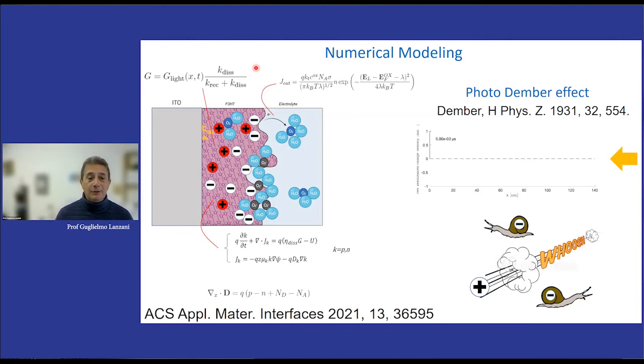When you have this kind of asymmetry, what happens due to the Lambert-Beer profile, which established a space gradient, is that diffusion is efficiently redistributing the positive charge everywhere in the field, while the negative charge does not move. So the illuminated surface will keep the sign of the negative charge, because from there, the negative charge is not moving. So that's why illuminating on one side or the other, you change the sign of the photovoltage.